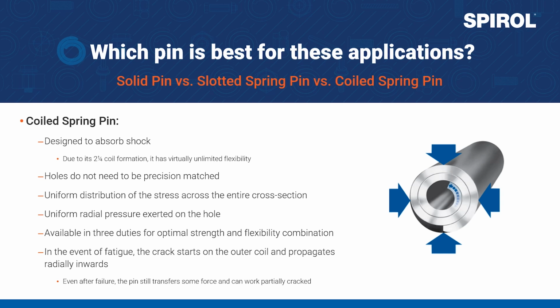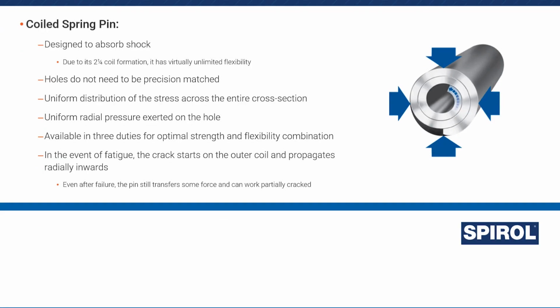Should the coil pin crack due to fatigue, which will require more time than competing products, cracking will propagate from the outer coil, typically within the shear plane, slowly work its way inward, and as that crack progresses through the coils, the coil spring pin will continue transferring loads until its cross-sectional area is reduced to the point at which shear occurs.